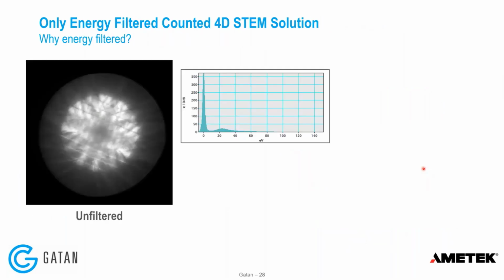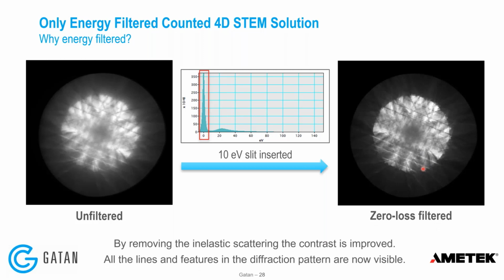Another advantage, as I mentioned earlier, with Gatan is that you can do filtered 4D STEM. And here is an example of two diffraction images. The one on the left is unfiltered and the one on the right is zero loss filtered. As you can see, all the haze in the background from the inelastically scattered electrons is removed in the diffraction image on the right. That is going to improve the signal to noise ratio in the diffraction images in the 4D STEM data set, and improve the quality of your 4D STEM data.